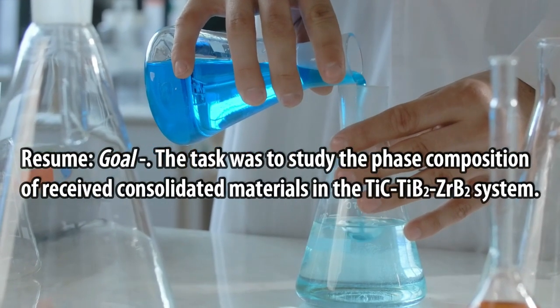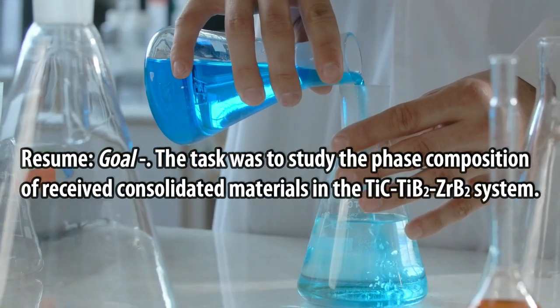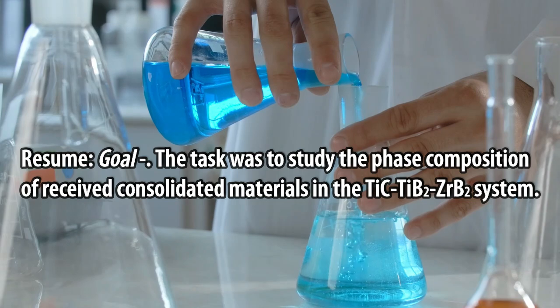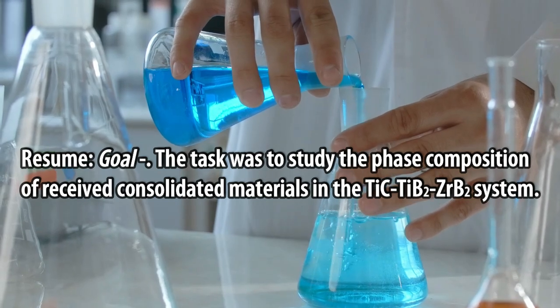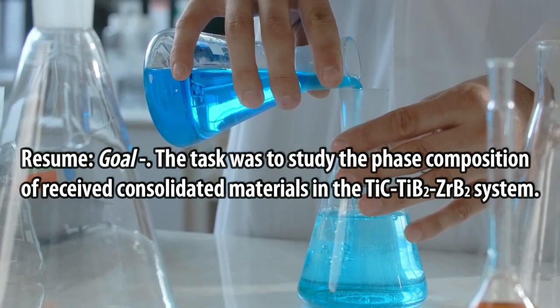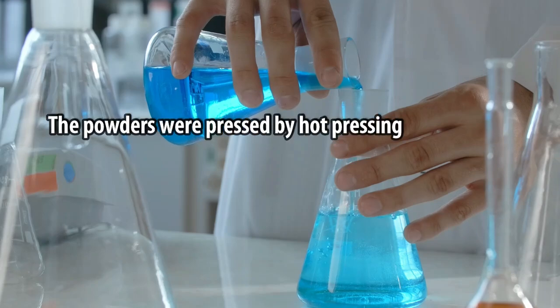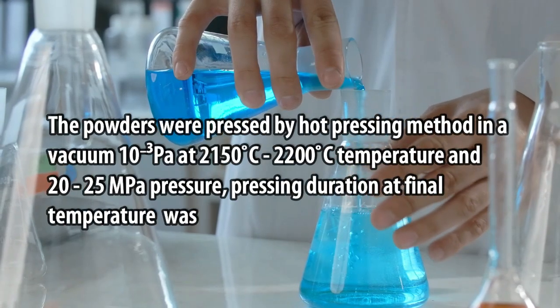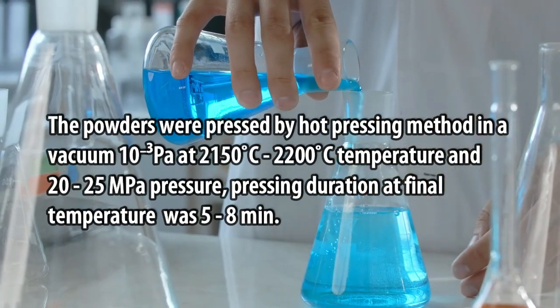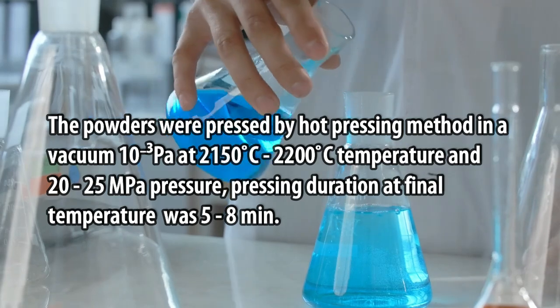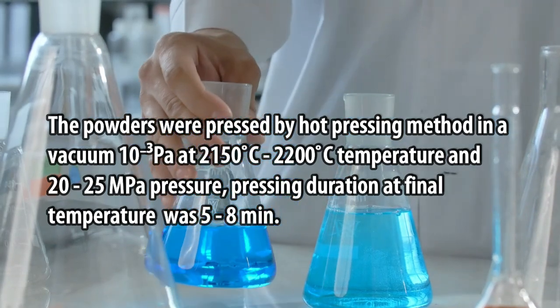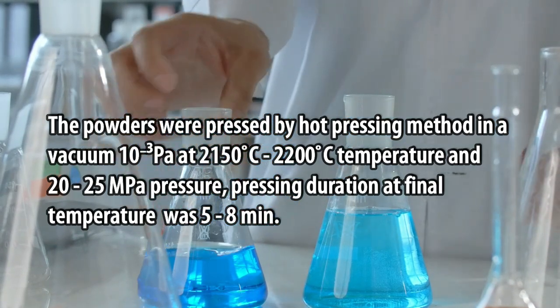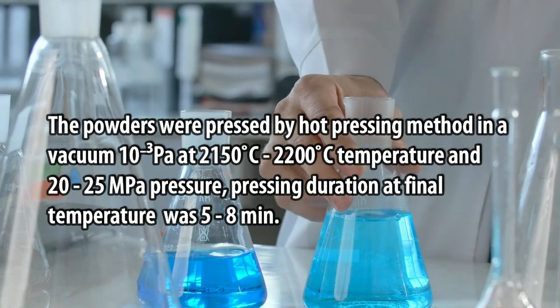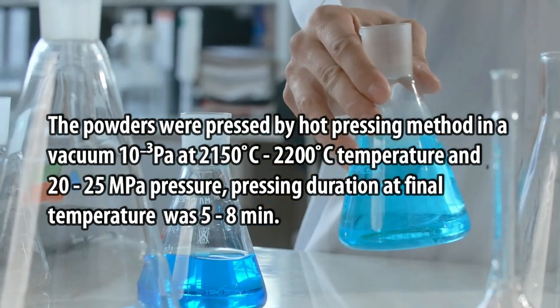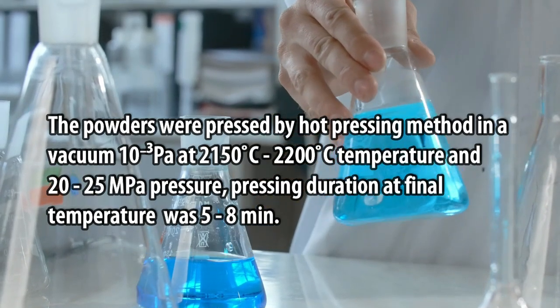Resume. Goal. The task was to study the phase composition of received consolidated materials in the TiC-TiB2-ZrB2 titanium carbide titanium diboride zirconium diboride system. The powders were pressed by hot pressing method in a vacuum of 10 to the minus 3 pascals at 2150 to 2200 degrees Celsius temperature and 20 to 25 megapascal pressure. Pressing duration at final temperature was 5 to 8 min.